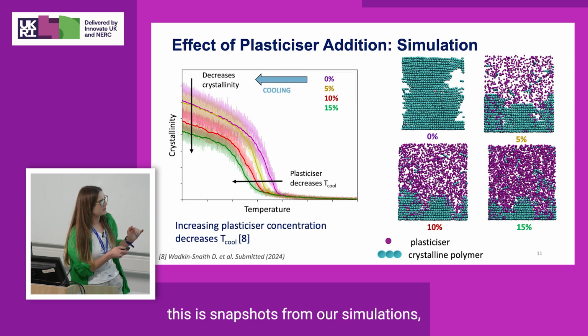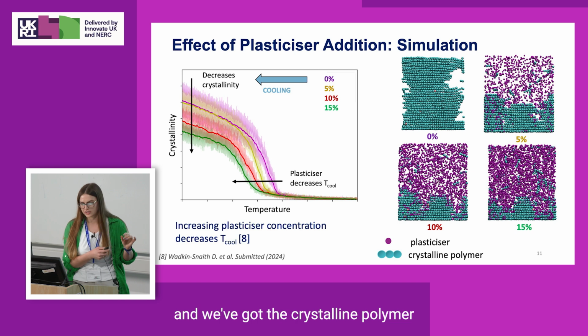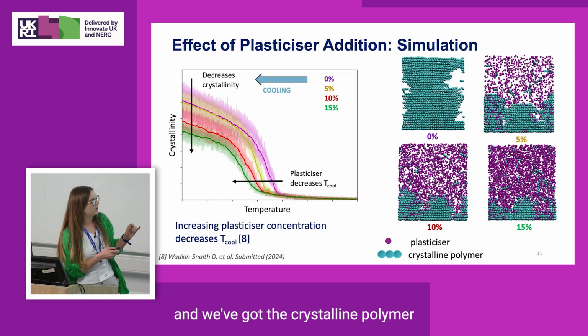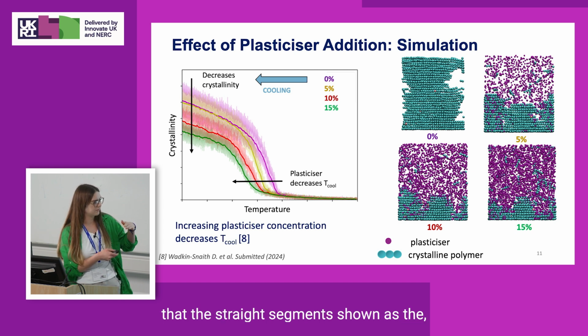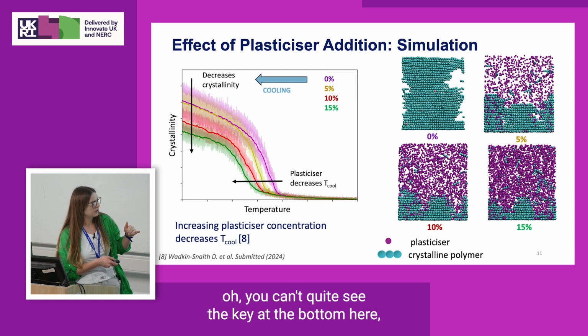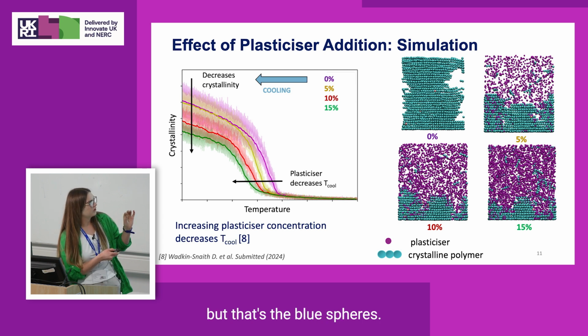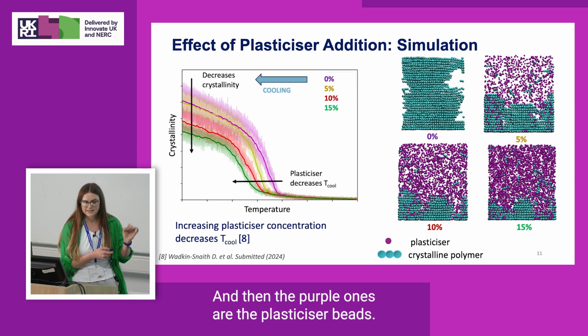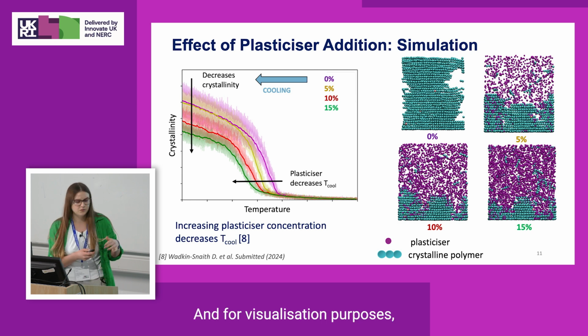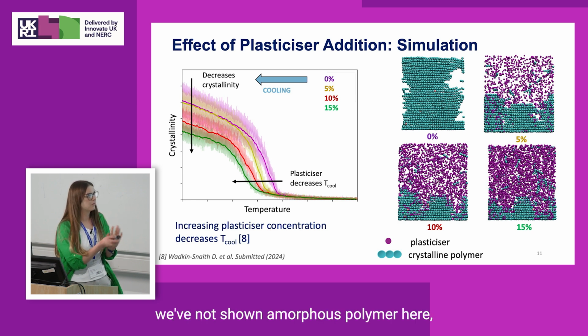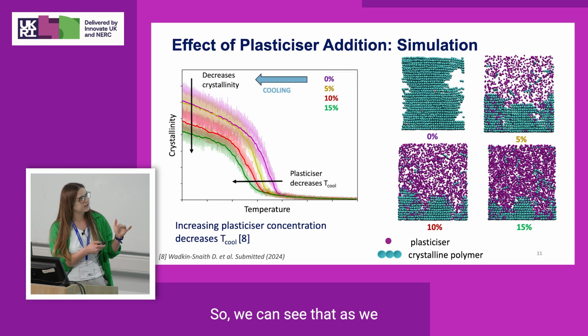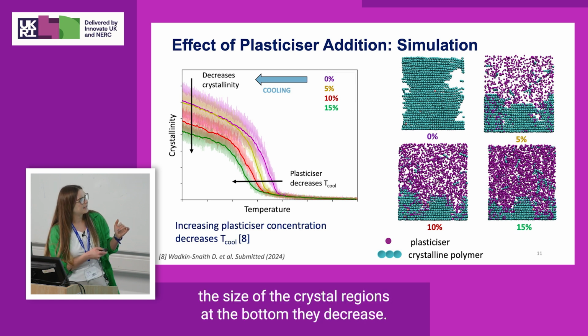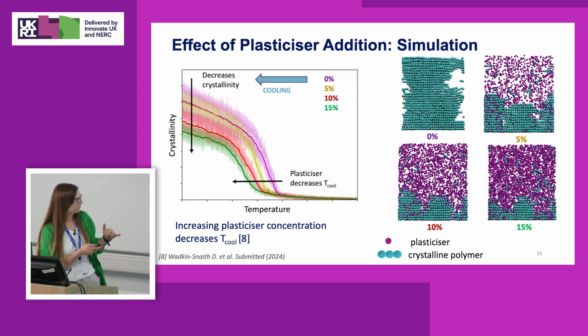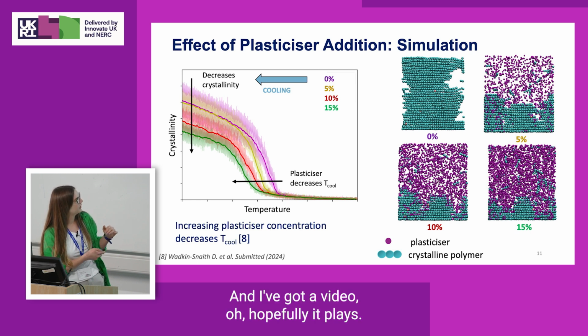In these diagrams, these are snapshots from our simulations, and we've got the crystalline polymer, the straight segments, shown as the blue spheres, you can't quite see the key at the bottom here, and then the purple ones are the plasticizer beads. And for visualization purposes, we've not shown amorphous polymer here, it's just the crystal regions. So we can see that as we increase the concentration of plasticizer, the size of the crystal regions at the bottom decrease. And I've got a video.